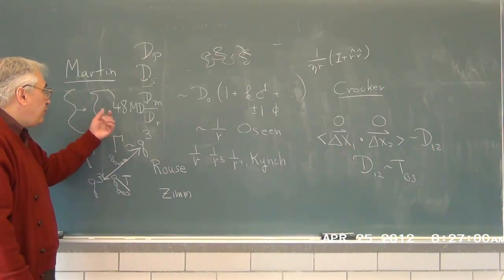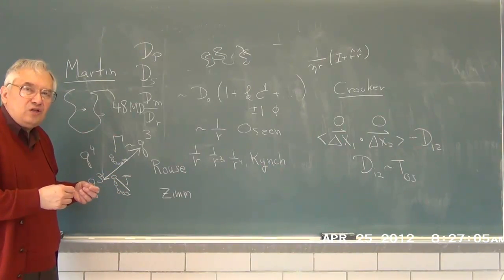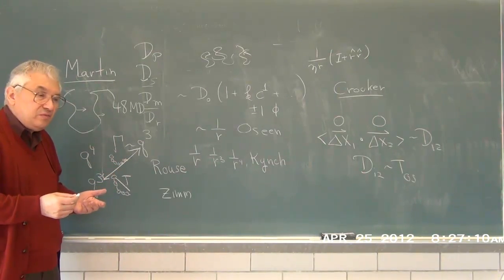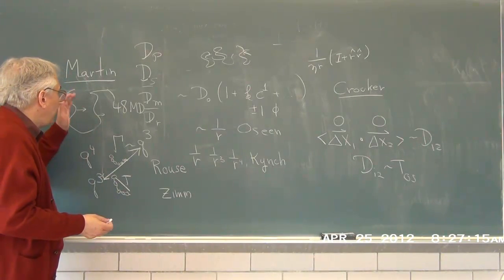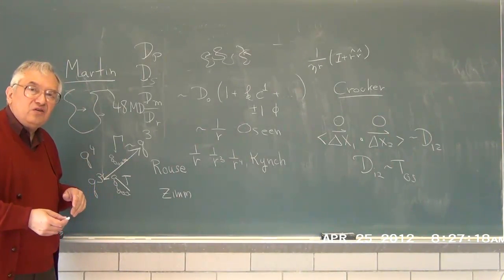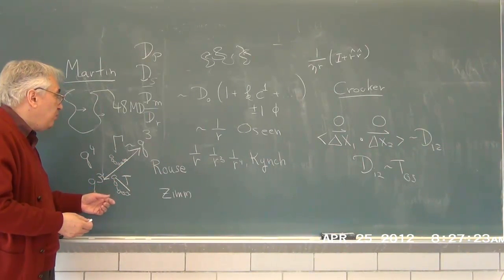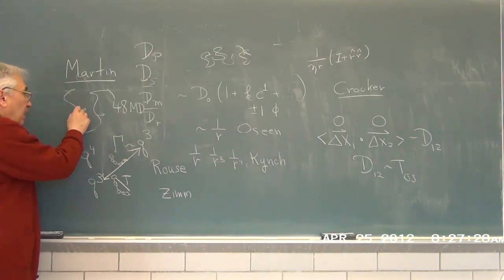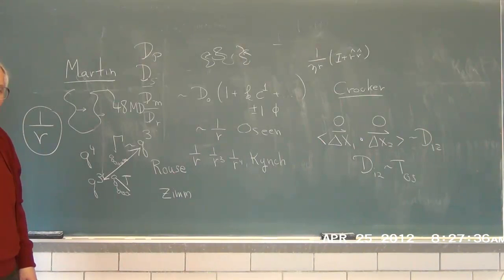And therefore, for this object in a solution where the hydrodynamic interactions ought to be screened, the matrix is very concentrated, very substantially entangled. If you believed in the screening, you'd say you should see non-interacting beads, Rouse behavior. In fact, you see Q-cubed behavior, and therefore, as Martin says, the hydrodynamic interaction between the beads must be falling off as 1 over R, the unscreened behavior.